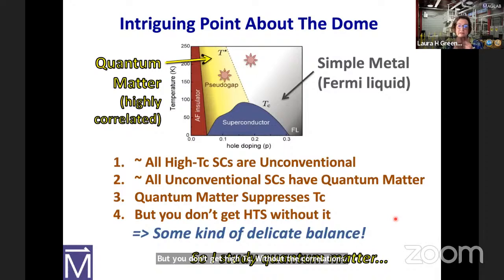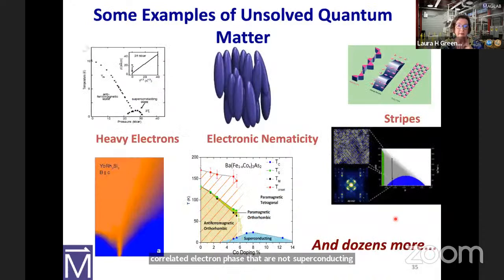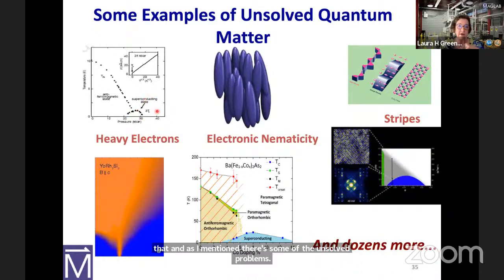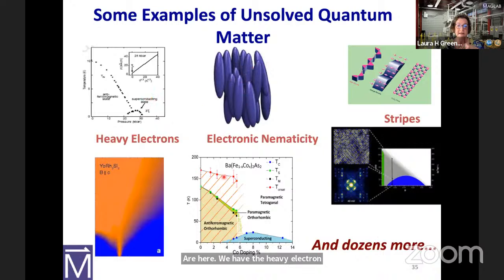So to me, it's understanding that delicate balance between the correlated electron phases that are not superconducting and the superconducting phase. That's why I study that. And as I mentioned, some of the unsolved problems are, here we have the heavy electron phase. I mentioned the electron nematicity. These are data from my laboratory, where we find this electron nematic phase lasts up to like 175 degrees when superconductivity is like 30 degrees. So some of these are very high temperature correlated phases. And I mentioned stripes and pseudogaps.